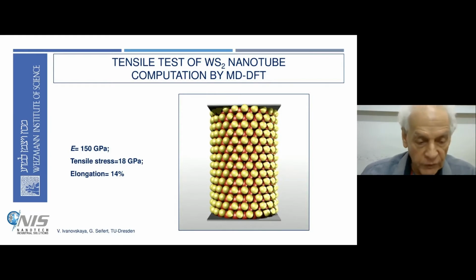Gotthard Seifert calculated the failure mechanism of this nanotube. He actually pulled these nanotubes, moving up here and down there, and you see how the tensile stress on this nanotube leads to failure immediately at the center. This was really the same mechanism we saw in our electron microscopy analysis of this nanotube.